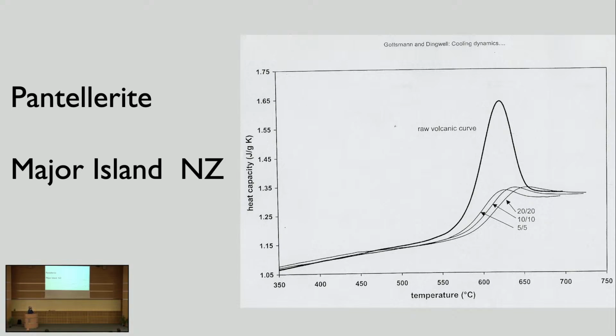And what you see here is a series of calibration curves of CP versus temperature, and then you see the raw volcanic curve, and you see how far away from this range of cooling rates the actual cooling in nature must have been, because you're way away from an extrapolation of the shape of those curves. So this is the slowest cooled rock we ever found, volcanic rock we found in nature. It comes from a place called Major Island, New Zealand, right next to White Island, the one that blew up a few years ago and burned a few tourists who were walking across the caldera floor at the time.